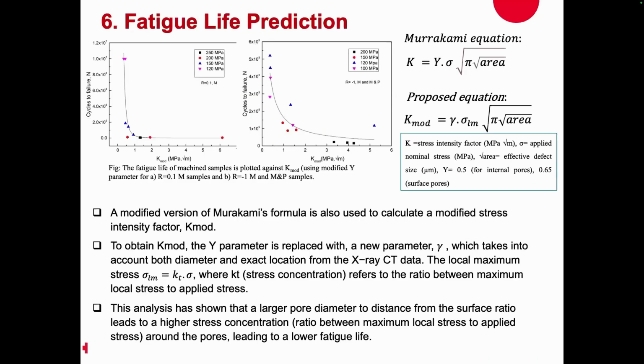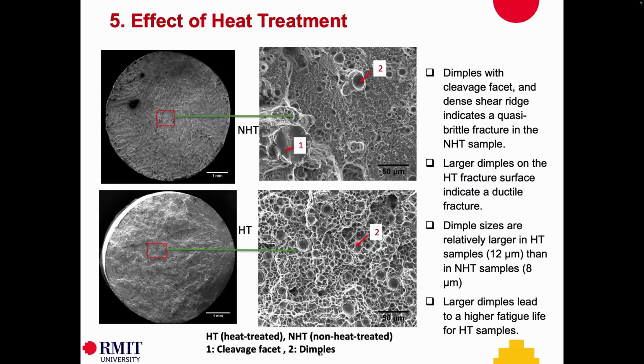With that, we have proposed finally, this is obviously a more fracture mechanics study, which I would omit, the formation of what we can see. If you have a non-heat treatment, the dimples have a cleavage facet and dense shear ridge, which promotes quasi-brittle fracture. But if you have a heat treatment, we can see more round dimples, which promotes more ductile fracture. And that's another mechanism by which heat treatment improves your fatigue life.